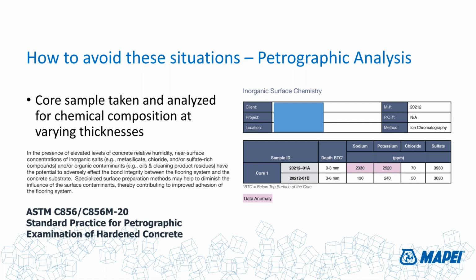This is the kind of stuff that should raise your spider sense and make all your feelers go off and say, I might have a problem if I install over a concrete slab that has a high level of these kinds of materials on the surface, whether it's a high pH or a high sodium or high potassium concentration. These are the kinds of things that are going to initiate this salt pump action on a concrete slab, causing it to have an impact on the adhesive performance, pulling moisture up on the floor, creating liquid underneath the floor, all sorts of bad stuff that's going on.